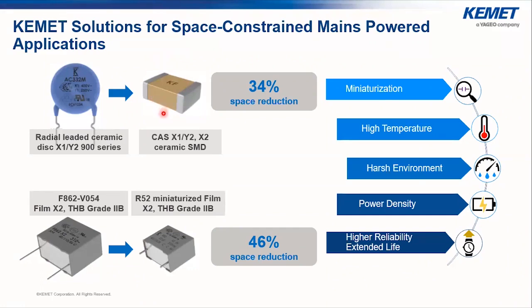So in November 2019, KEMET released a new miniaturized safety design, a surface mount ceramic capacitor that allows 34% space reduction compared to the radial leaded ceramic disc safety capacitor. And in September of 2020, KEMET released the newest miniaturized film suppression X2 capacitor, whose advantage is not only the downsizing, allowing an average of 46% space reduction compared to the actual F862V054 series, but also that this series is qualified and able to withstand a THB grade 2B, which means 85 degrees, 85% relative humidity at rated 310 VAC voltage for 500 hours.